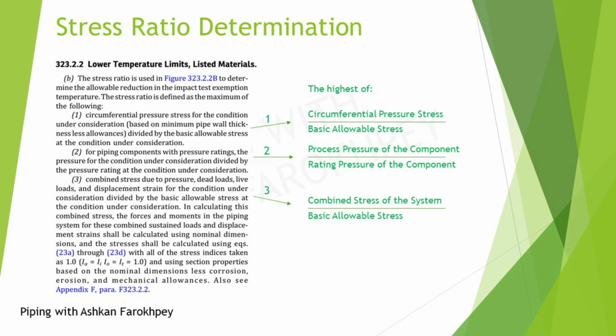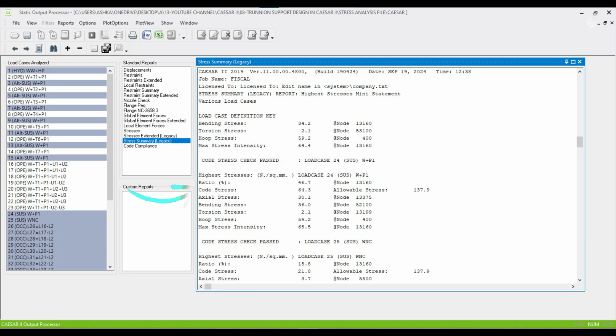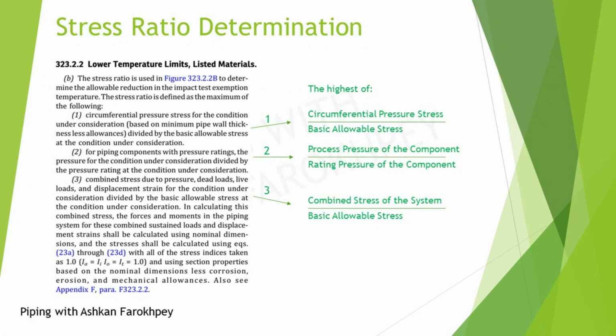Don't tell yourself that since the internal pressure of my system is low, the stress ratio is also a small quantity. This factor can be raised due to many factors, including the weight of the system, expansion and contraction stresses, or even occasional load cases. So, by going to this section of your Caesar II, check the exact amount of the stress ratio in your system in all load cases. As you remember from my other tutorials, except for OPE load cases, the rest must be checked for stress quantity. In other words, by defining the correct load cases in your Caesar II software, the highest stress ratio in your load cases can be used here for finding the reduction in exemption temperature.